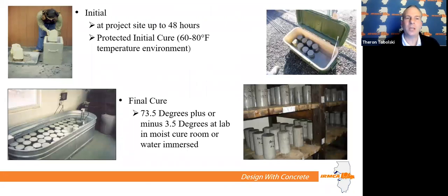Part of that standard is how you actually store the cylinders, right? So we cast them. Let's just talk about a concrete project job site. So we casted our cylinders. They can only sit on the project for up to 48 hours. And during that 48 hours, they must be kept at 60 to 80 degrees. That rarely happens, but that is one of the leading causes on why we get failed cylinder breaks from a job site. So it is very important, if you're an engineer and you're specifying concrete, these rules need to be followed here.